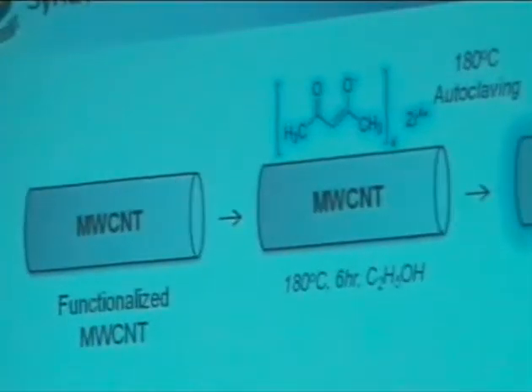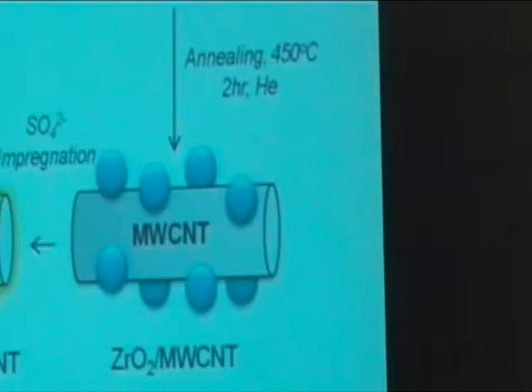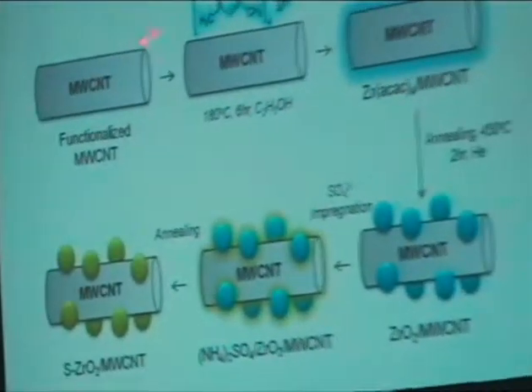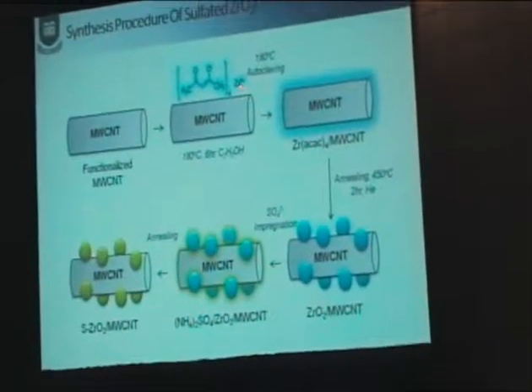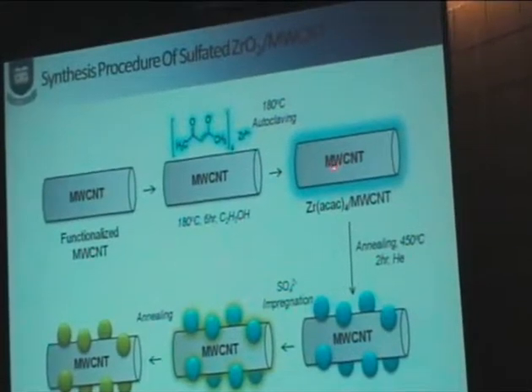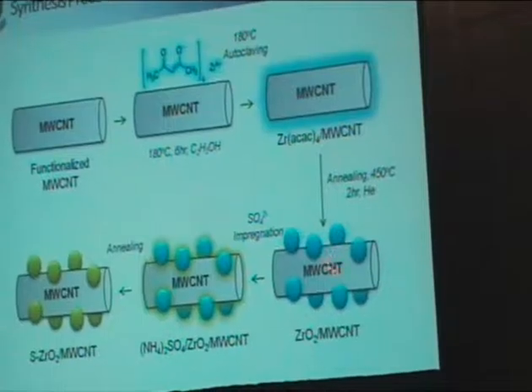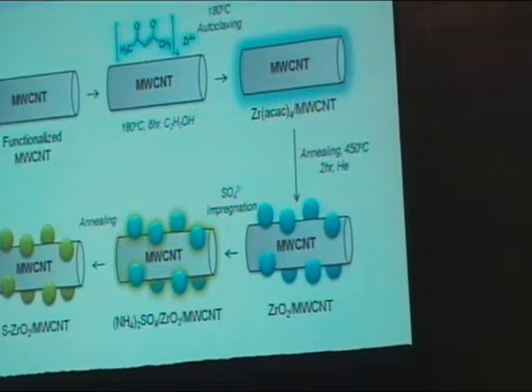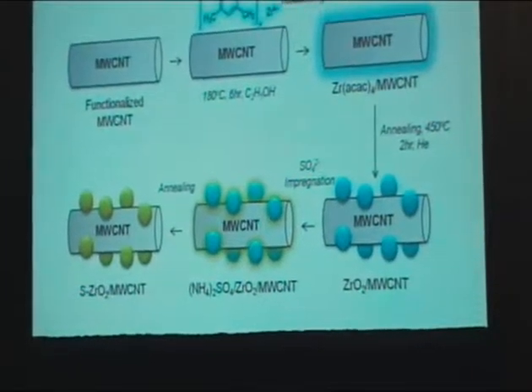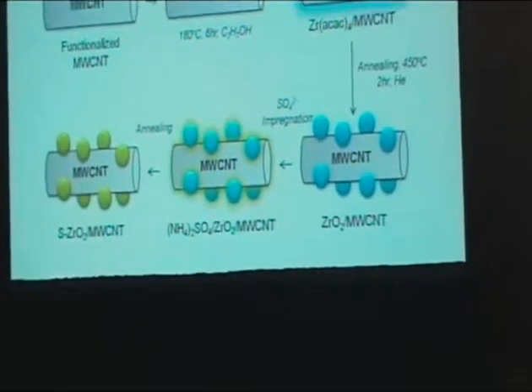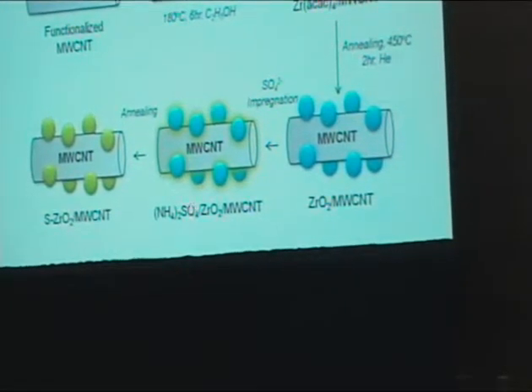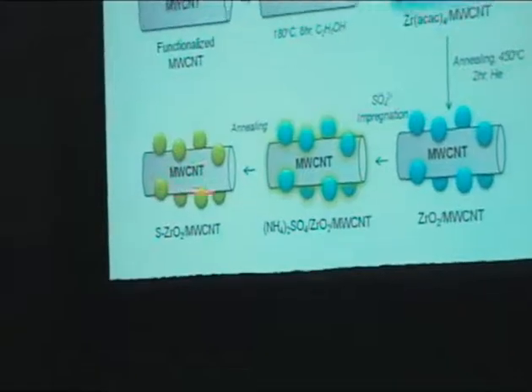So this is a cartoon on how we make these materials. The support is multiwalled carbon nanotubes, which are functionalized by oxidative nitric acid. We then graft a zirconium precursor, that's a zirconium acetylacetonate, onto those functional groups, and then that is annealed at 450 for 2 hours to crystallize the zirconium oxide. We can put in a little oxygen, but we can't use the traditional calcination because we'd burn up the tubes. And then we impregnate with ammonium sulfate and repeat this annealing at 450, and that's the catalyst that I'm going to be talking about. But I won't say any more about the preparation itself.